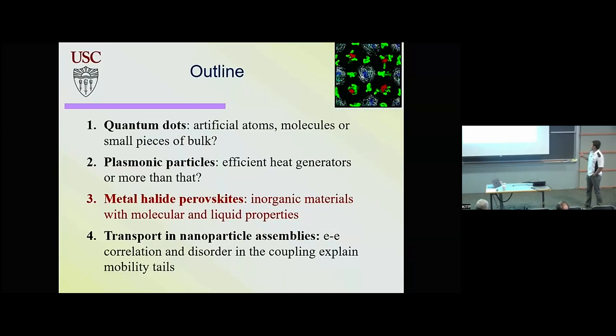But at the same time, you have a pretty big space here, which you fill either with a small organic molecule or a large inorganic cation. And this small organic molecule can rotate. It has a dipole moment, an uneven charge distribution. So you can think of it as a liquid because when you put a charge in this material, the dipole moment of the molecule can rotate, and then it can screen. So you can talk about solvation if you come from the liquids community. From solid state physics, it's a polaron, but it's a very large polaron. So it's also very good for dissociating excitons because you have very large screening. You have holes and electrons, but they're all screened by the medium, by the material, and you separate charges very fast.